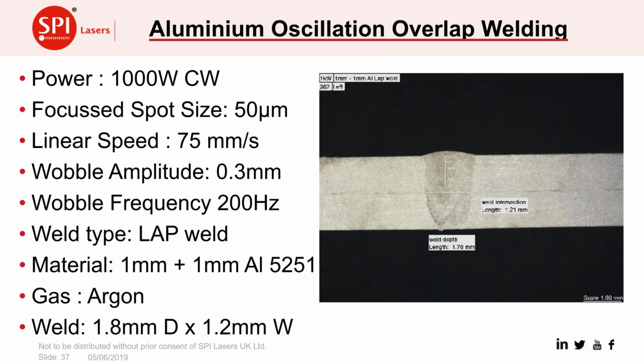And again, in this case, we were only using a kilowatt, but we had two 1 millimeter thicknesses of 5251 aluminium. You can see that we've been able to produce, again, over a millimeter wide at the intersection here. And what's interesting about this type of weld is that you've got very good control over the depth. So you see we've produced a good weld intersection width, but there's no witness through to the back surface of